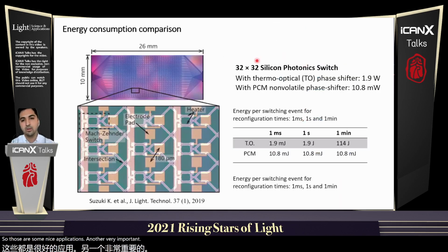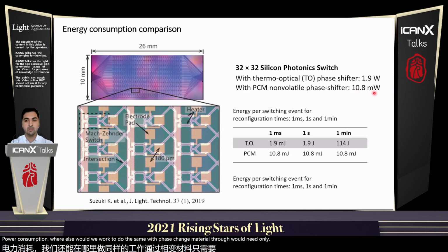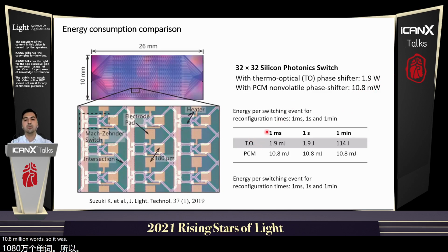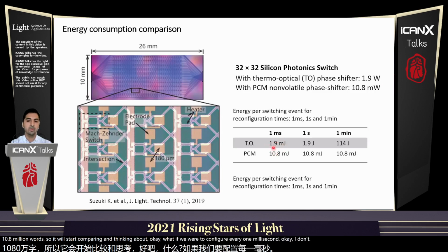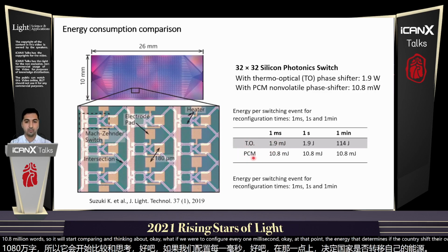Another very important thing about non-volatility is the low energy consumption. In this case, I'm showing a 32 times 32 silicon photonic switch that was demonstrated in this paper using thermo-optical phase shifters. They required 1.9 watts of power consumption, whereas if we were to do the same with phase change materials, we would need only 10.8 milliwatts. If we start comparing and thinking about what if we reconfigure every 1 millisecond, at that point the thermo-optical phase shifter outperforms phase change materials.